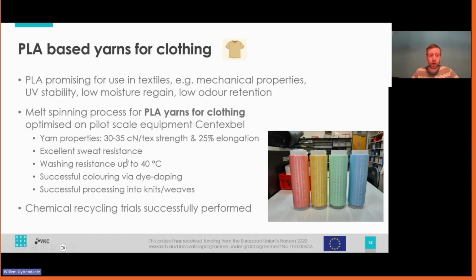What we see with these fibers is that we also have excellent sweat resistance, wash resistance up to 40 degrees. We see that if we wash a few times, 60 degrees is possible, but it does change the hand feel of the final clothing. We can color it via dope dyeing with all kinds of different pigments, and can successfully process it into different knits and weaves. And to make sure that this clothing can also be recycled, we also did chemical recycling trials at Futero.